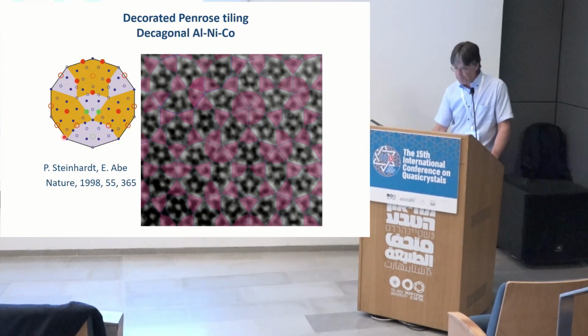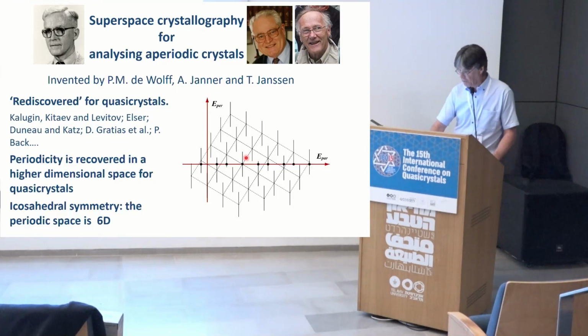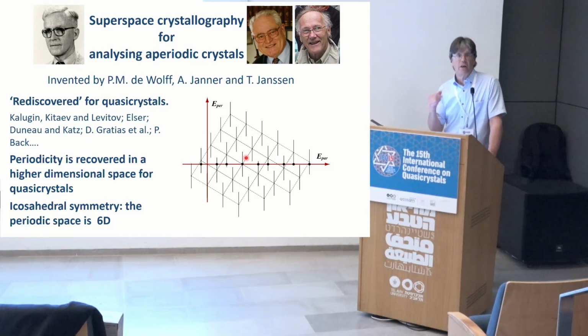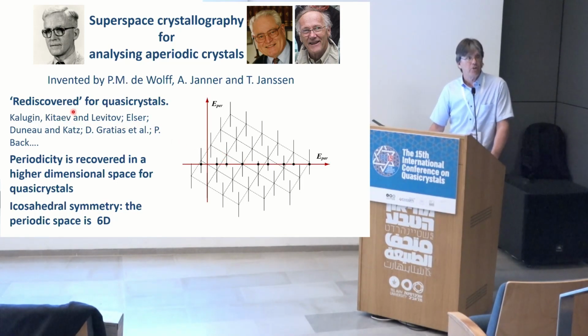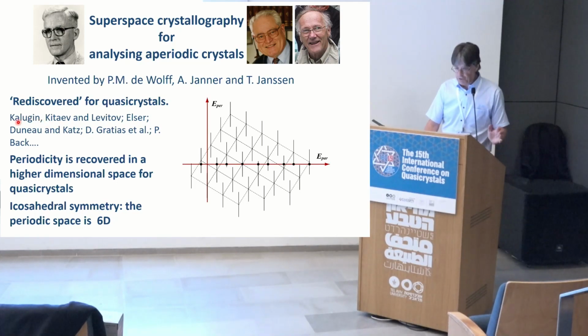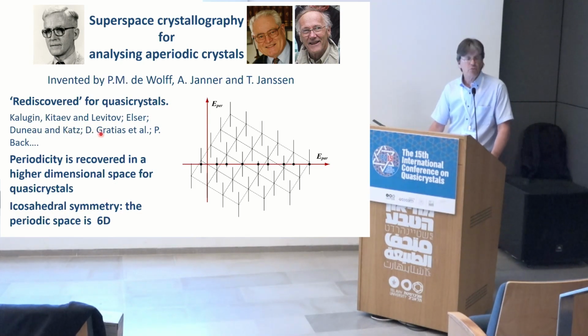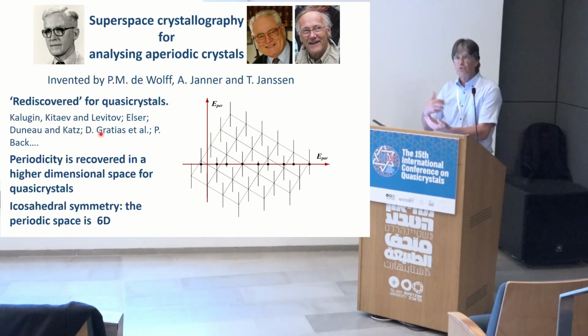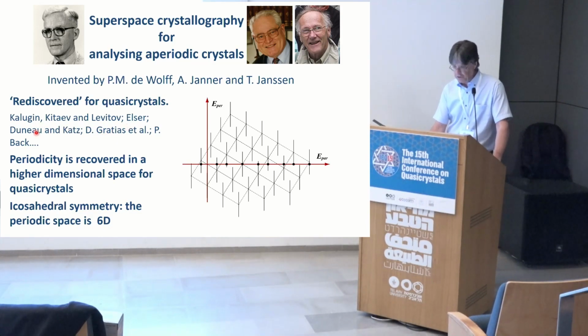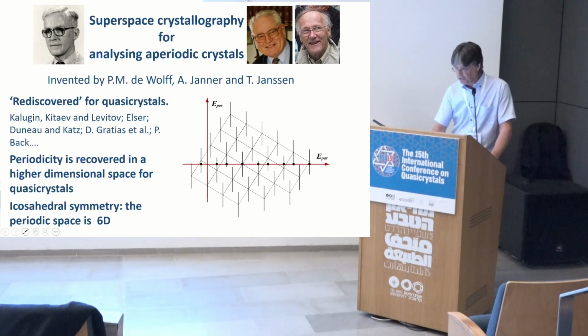I'm just showing here one example of Paul Steinhardt and Eiji Abe on the aluminum nickel cobalt, where they have decorated the tiles with atoms and superimposed them on the electron micrograph. But the most fruitful approach has been using the superspace crystallography, which in some sense has been rediscovered by quasicrystal people. I'm just putting some names here: Kalugin, Kitaev, Levitov, Elser, Duneau, Katz, and Denis Gratias, who was the first one to really use this technique to solve structure. Peter Bak also. And again, the trick is that the periodicity is recovered in a higher dimensional space.